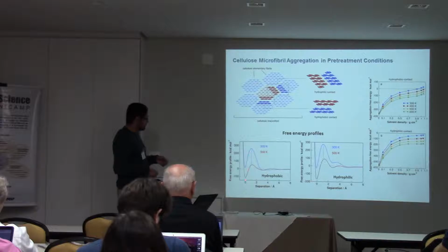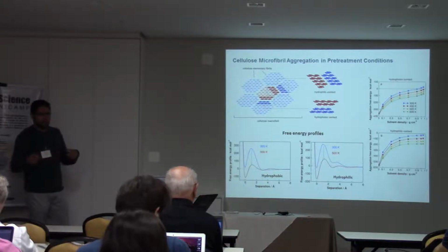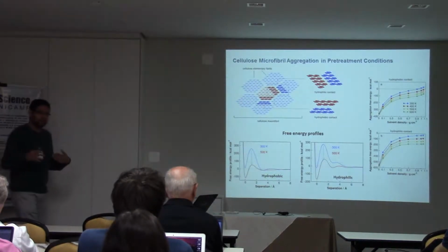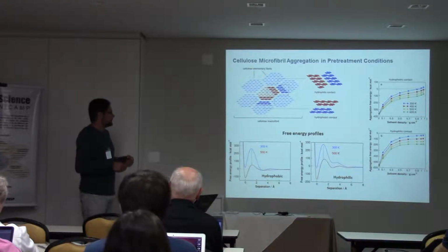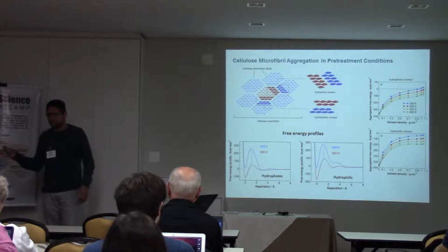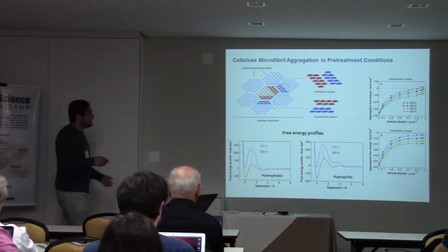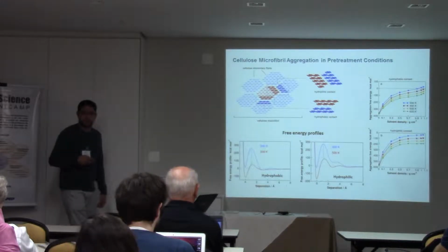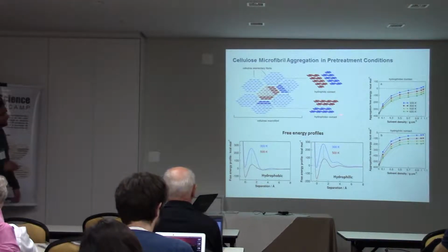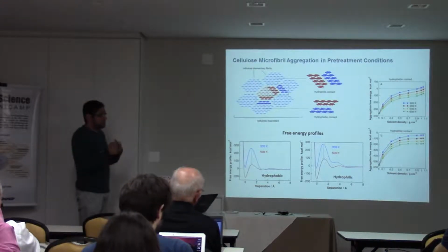And from this free energy profile, we can also obtain, for example, the free energy of aggregation in a lot of different conditions. This is what I show here, for example, in a range of temperature and a range of density that covers different pre-treatment conditions. And you can see here that, again, the hydrophobic arrangement is much more sensitive to changes in the thermodynamic conditions, and it can also change qualitatively.